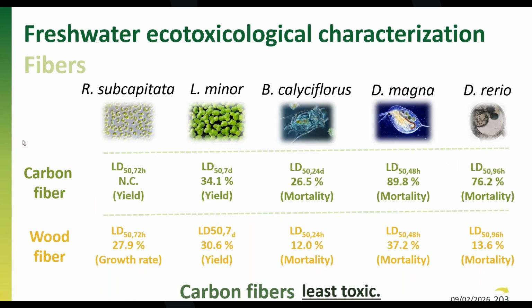But these were interesting results because we could spot that the carbon fibers were overall least toxic to the aquatic organisms when compared with the wood fiber, which was probably related with the fact that some of these wood fibers originate from wood waste, and sometimes these wood wastes have some toxic materials like metals that come from the inks, for example, that are used in this wood, and probably the toxicity that we saw here was related with that.